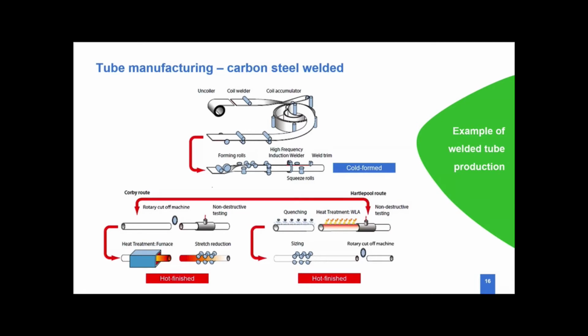So this is where instead of using a billet like a seamless mill uses, we take a coil of steel, we form it into the tube profile, we use a high frequency induction welder, which means it superheats the ends of the strip and we squeeze it together. There's no filler material used. That then produces a cold form tube. We then take that tube, which has a heat affected zone, a weld seam, and we put it through a furnace and take it up to temperatures of about 1000 degrees C, which allows that weld seam to disappear. So a welded tube can be seen as being equivalent to seamless only if it's gone through a heat process, a normalizing process.